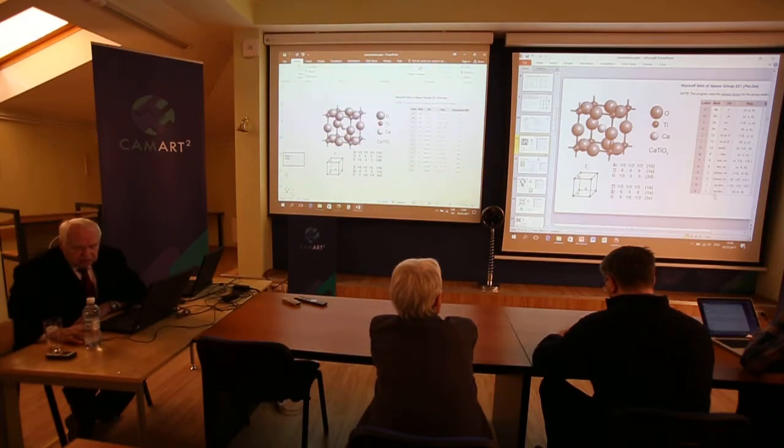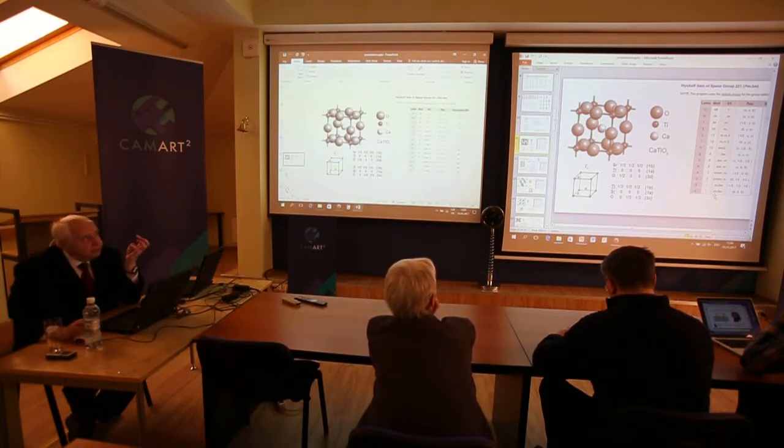So, what is crystalline structure? Crystalline structure is given when you give the space group, in the number of which you have the type of lattice and point symmetry of the whole space group, and then you have the distribution of atoms over Wyckoff positions. How many parameters do you need to fix when you try to give information about crystalline structure?